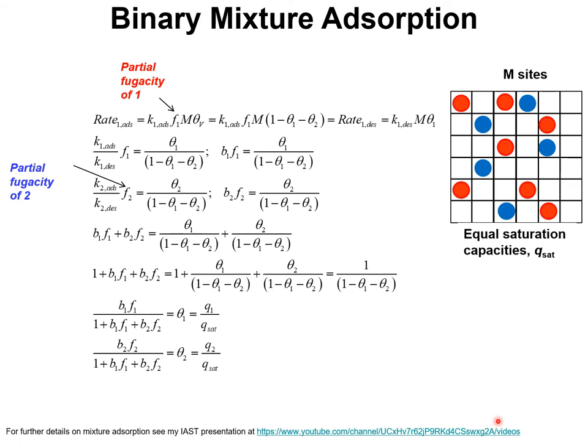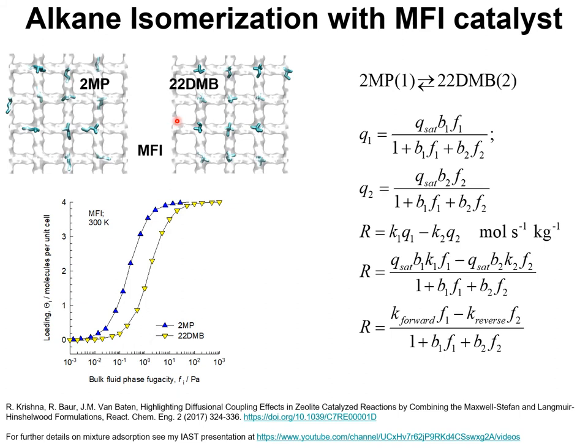Having this background, let's consider the derivation of the Langmuir-Hinshelwood kinetic expressions. We set up the kinetic expressions for alkane isomerization using an MFI catalyst, considering the isomerization of 2-methylpentane to 2,2-dimethylbutane. Both components are preferentially adsorbed at the intersections between straight and zigzag channels per unit cell of MFI zeolite. There are four intersection sites, and the unary isotherms for 2-methylpentane (shown in blue) and 2,2-dimethylbutane (shown in yellow) show a saturation capacity of four molecules per unit cell.